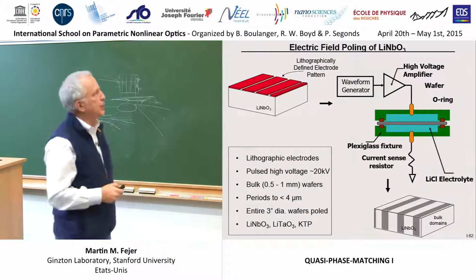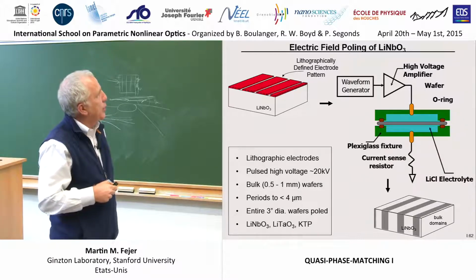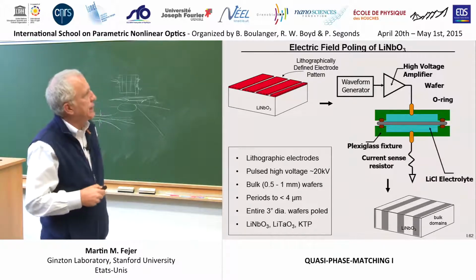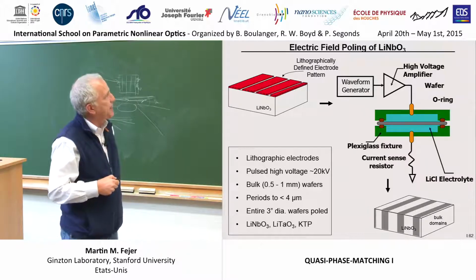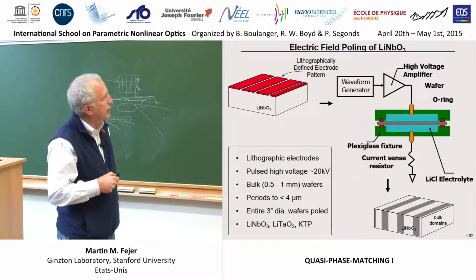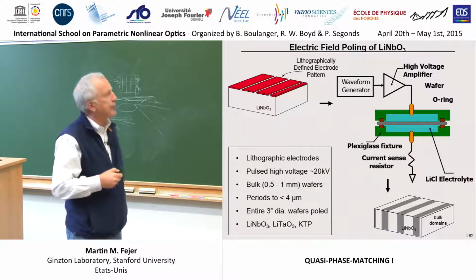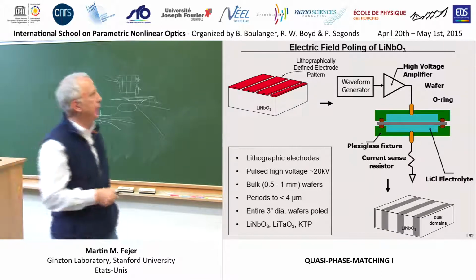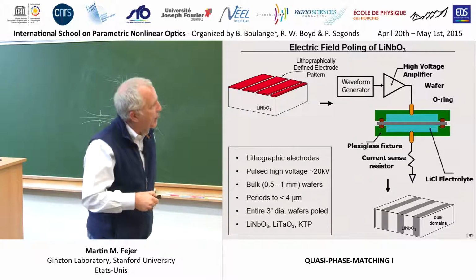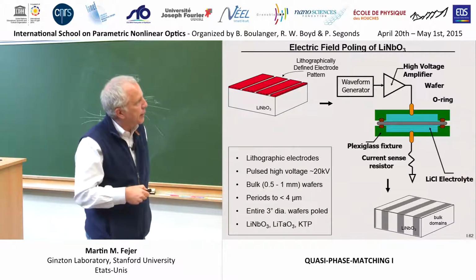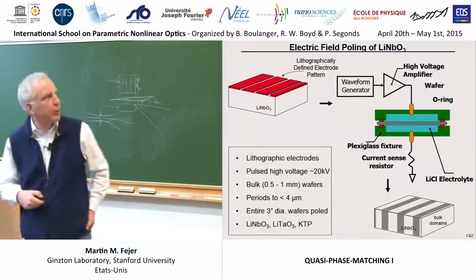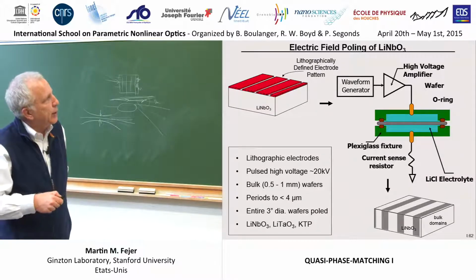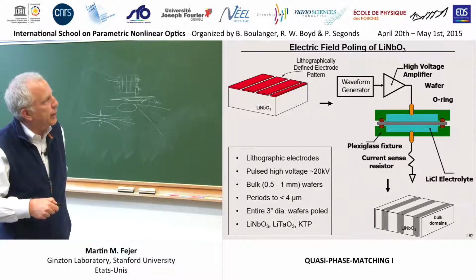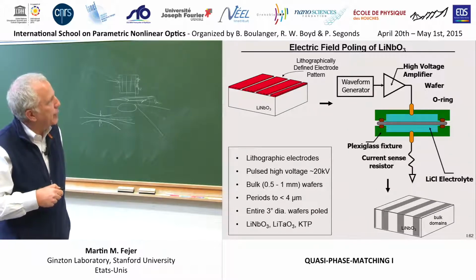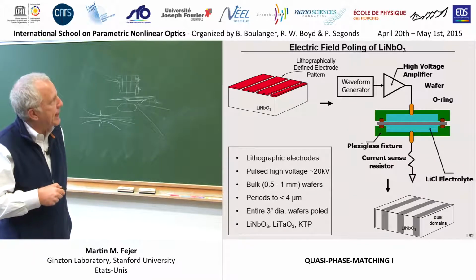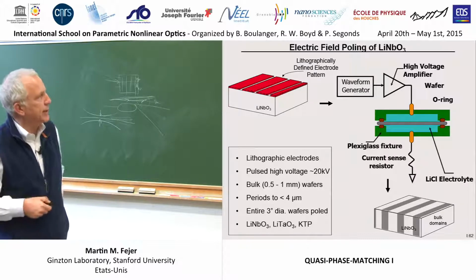So the basic process one does is to pattern a periodic electrode. Actually, in our case, we usually pattern an insulator, just photoresist, with gaps where you see the original wafer exposed. You put that patterned wafer in this fixture here, which is filled with an electrolyte, typically lithium chloride and water, and then you apply a high voltage pulse to the liquid, which is making contact with your substrate in these gaps and not contacting the substrate where these insulators sit.